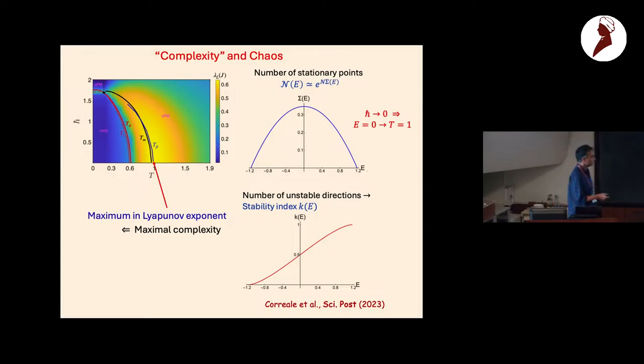But let me just end, with one or two slides. As I said earlier, these people, after this work, tried to find out the relation between this maxima and the complexity. They did quite standard calculations of this complexity, which is the number of stationary points and also the index of the stationary point. They did this calculation in a micro-canonical way, as a function of energy, unlike here, which is as a function of temperature. But you can connect this energy to temperature as they do, and what you find is that E equal to 0 exactly corresponds to T equal to 1 in this thing. There you have the maxima of this complexity, and also you have mostly half unstable and half stable saddles. And that's why this chaos is maximum.